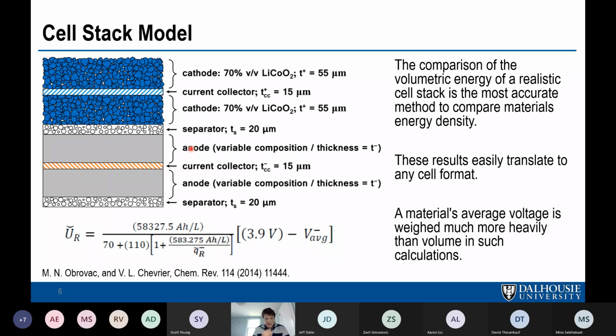And so Vincent Chevrier and I worked that out in a paper we published. We just built up a standard cell stack. So the separator and the anode, double-sided coated anode, another separator and a double-sided coated cathode. And this is sort of like a unit cell in a wound or a stacked lithium-ion cell. You can take this unit and just repeat to build up a cell. And then we calculate the energy density of this thing for some standard cathode with some standard porosity. And if you do that, you get an equation that looks like this for the energy density of the stack.